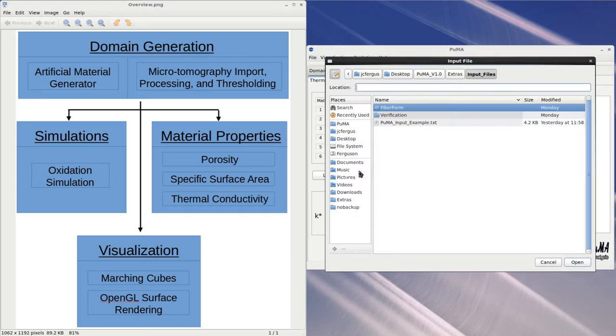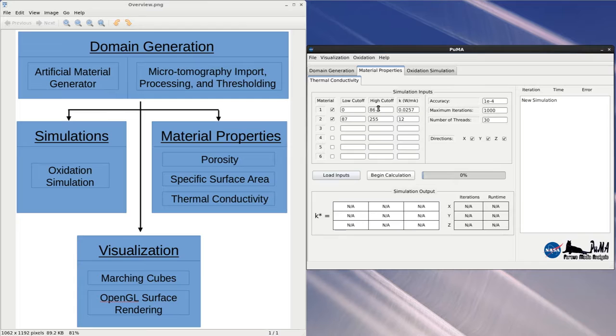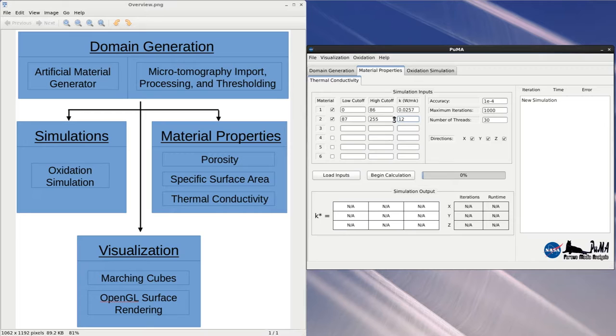To run the simulation, you have to select how many materials are in use. You then have to select the low cutoff and high cutoff for each material, as well as the conductivity for each phase. In this case, we're running with carbon fibers at a grayscale of 87 and above with a conductivity value of 12, and air for the voids with the conductivity value of 0.0257, which is the value for standard atmospheric conditions.